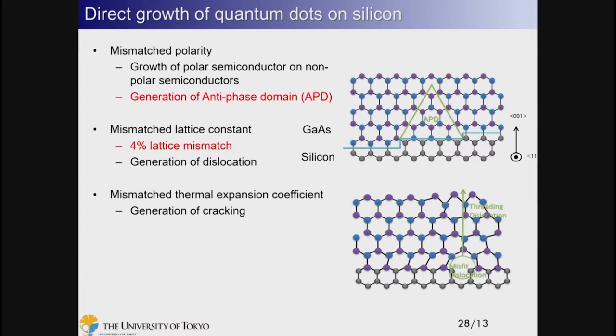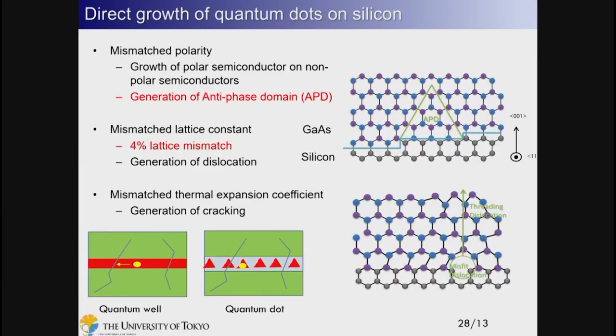So far I have been discussing flip-chip bonding and also wafer bonding techniques. Our dream is to realize direct epitaxial growth of the quantum dot structures on silicon or SOI. But direct growth of quantum dot lasers on silicon has various problems. Of course, today I don't discuss the details, but I just mention the mismatch of the polarities, the mismatch of the lattice constant, and the mismatch of the thermal expansion coefficient between gallium arsenide and silicon. Indeed, even 30 years ago, several groups tried to realize quantum well lasers on silicon, but they failed. But now we could succeed in realizing III-V lasers on silicon by utilizing quantum dot structures.